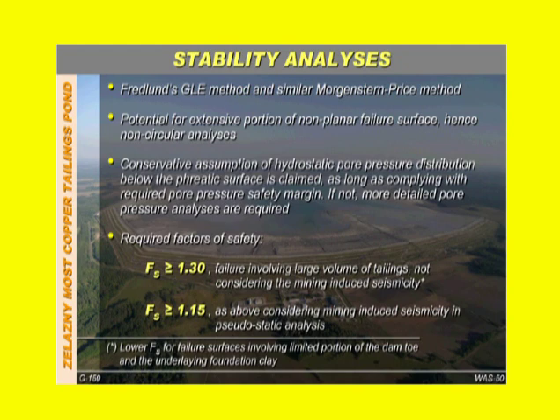The required safety factor for failure involving a large volume of tailings, not considering the mining-induced seismicity, must be 1.3 at least. When we are considering the mining-induced seismicity according to the Polish regulation, even using an extremely conservative pseudostatic approach, we must stay above 1.15. This is causing us some problem.